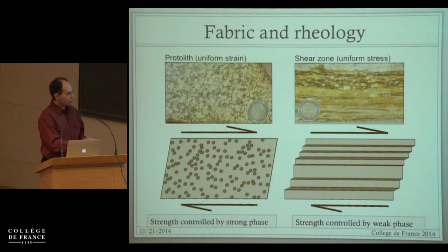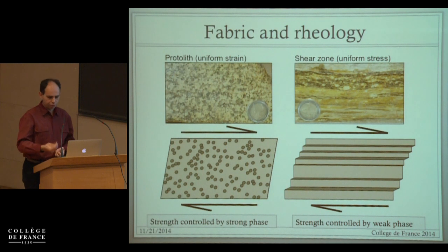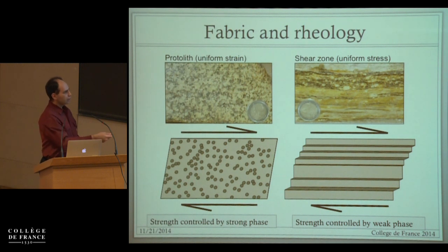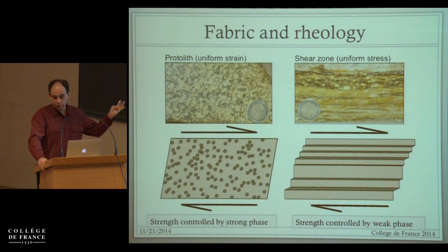But what we've shown recently is that if this weak phase happens to have a highly nonlinear rheology, you could have an increase in the deformation rate. So you start with the same stress and you change the fabric, and your strain rate could increase by many orders of magnitude, way too many to mention actually. It's kind of scary when you do the calculation. But basically you could have a very weak rock here if the material is highly nonlinear, and micas and phyllosilicates, the minerals present in these bands, are extremely nonlinear.